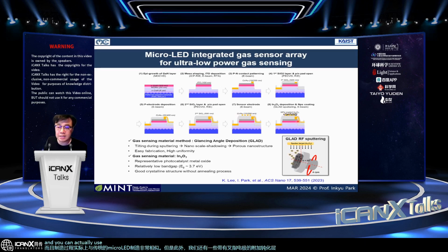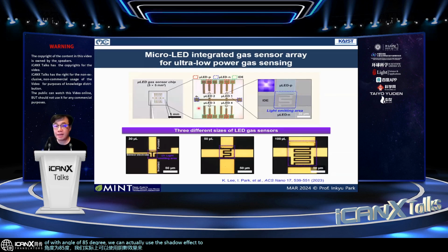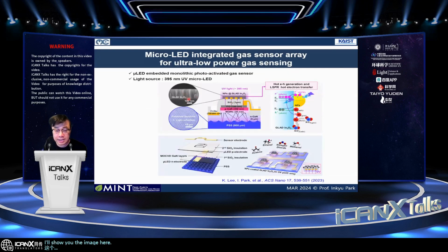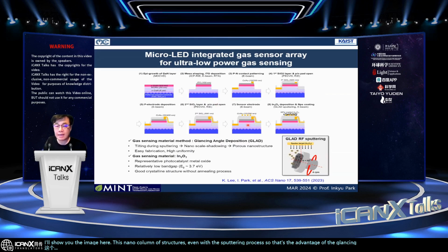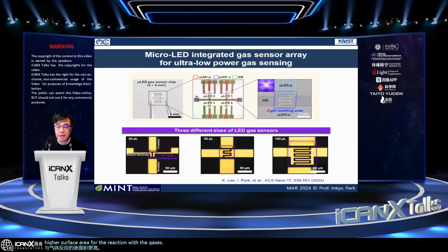And you can actually use various sensor materials, but here we use the glancing angle deposition using RF sputtering. So by tilting the substrate with the angle of 85 degrees, we can use the shadow effect to fabricate this, I'll show you the image here, nanocolumnar structures, even with the sputtering process. So that's the advantage of the glancing angle deposition, to make a higher surface area for the reaction with the gases. So this is a fabrication result.